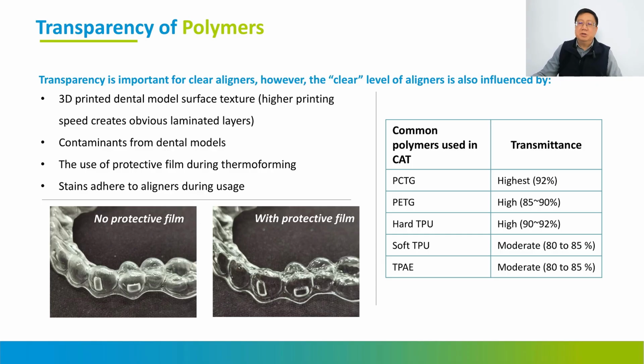And of course, the material itself is very important. The material comes from different suppliers, with different transparency. Some materials use bio-based polyols, which are naturally a little bit yellow in color. But if you use petrochemical-based polyols, then they have higher transparency. On this table, you can see their transparency is normally from 85 to 90%. This is good enough to be a liner.